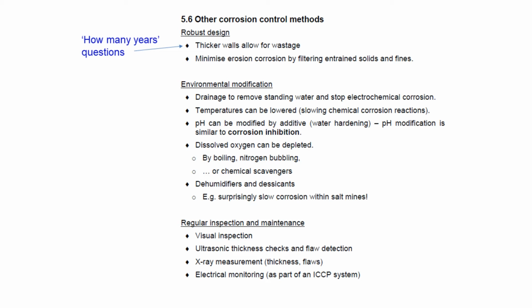What else can we talk about? Environmental modification. So corrosion is chemistry. So one thing we can do to slow it down, in the same way we can slow down almost all chemistry, is to decrease the temperature. So if we have a process stream which at some point we're going to cool it down, or we don't mind if it's cool it down anyway, then we should cool it down as early as possible so that it's less corrosive to the metal downstream. We can do some things which are described as corrosion inhibition, changing the pH, or removing dissolved oxygen. In some cases, we might be able to do environment modification by removing water completely.